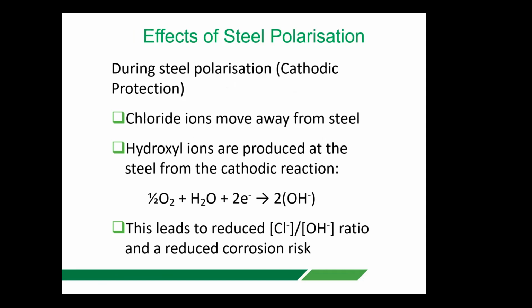So what was the background to that development? Well, we know that when we apply polarisation to the steel, i.e. cathodic protection, the chloride ions being negative and the steel being also negative, they start to move away from the steel. Chlorides are the main corrosive element, if you like, when we come to steel reinforced concrete. Equally, we start producing hydroxyl ions at the steel surface because of the cathodic reaction. As long as you have oxygen and water, you will produce hydroxyl ions. So that hydroxyl ions would increase the alkalinity around the steel reinforcement.